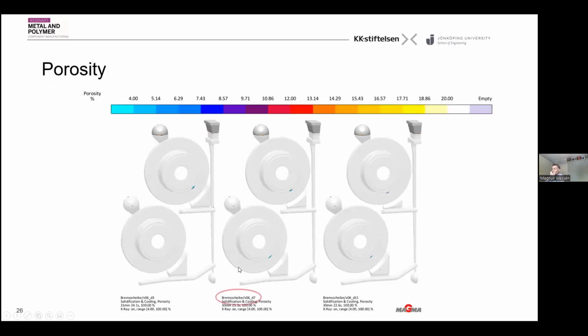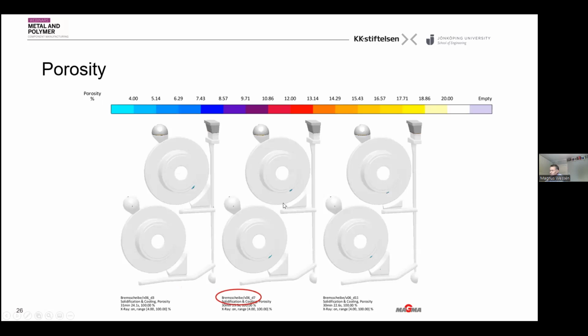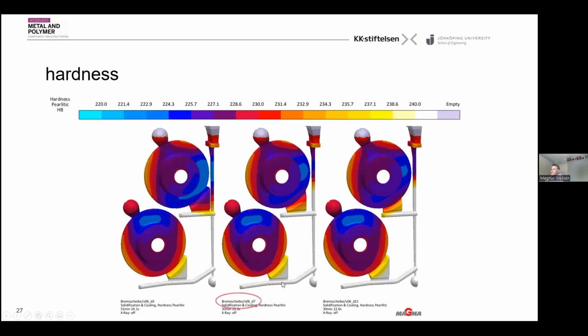These are what we can call the Pareto line of designs, which could give interesting results. And then this shows design number 7, which was, I think, maybe the smartest solution. You still have some porosity, but it is at least at minimum, and you have the minimum variation in the hardness. It's the pearlitic hardness for this gray cast iron disc. So in this way, they could both reduce porosity as well as the hardness variation.